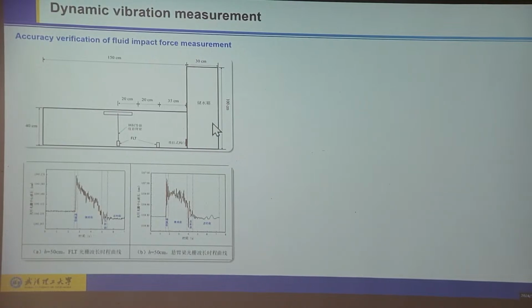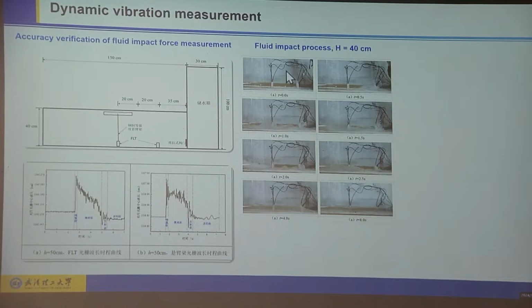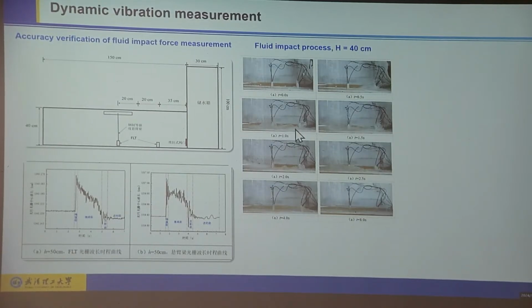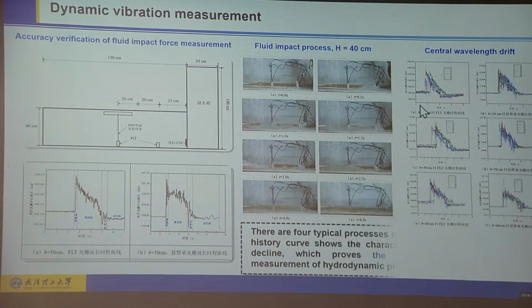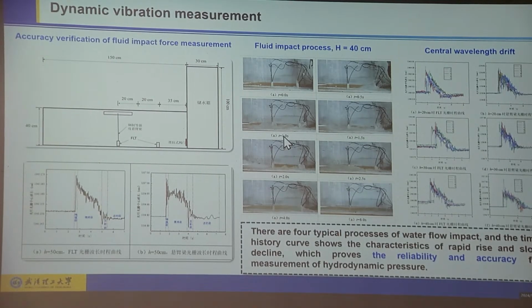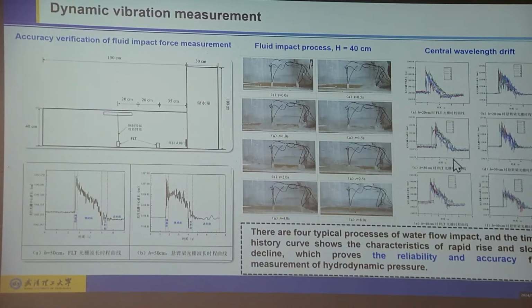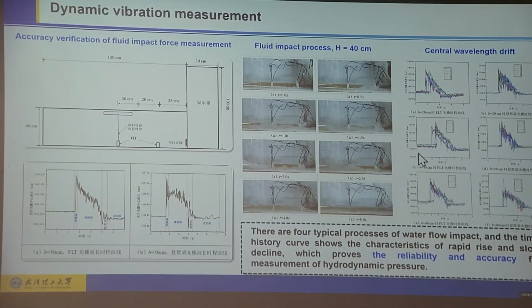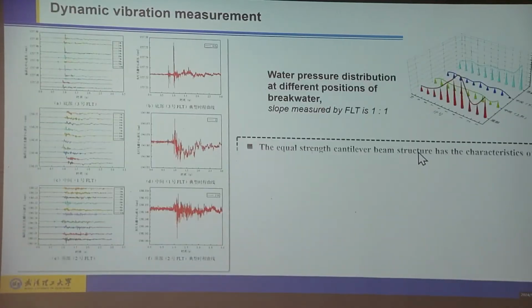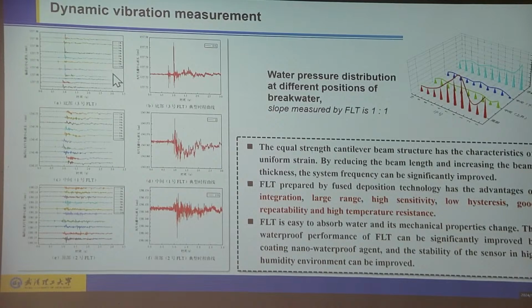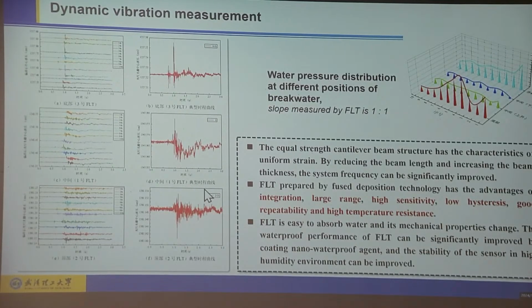In this model we have some water inside, and the impact loadings. We can measure the dynamic loadings in different stages. You measure the loading response. So this is the result. We get the result from our device. So this device can measure the dynamic loadings and the deformations, and also you can measure the pressures in geotechnical engineering. So at different times you can get different measurements, also the water pressure distributions, and also the changes of the deformations in different parts. So we do this analysis. It's good in water environment conditions.